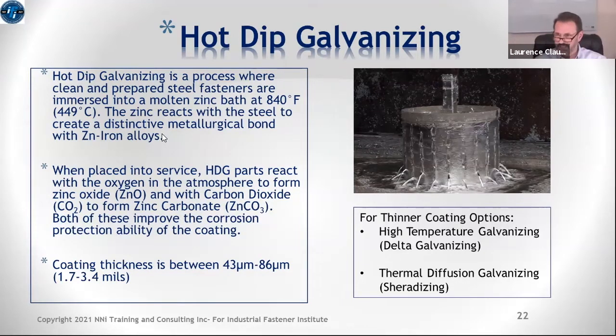If fitment is an issue, but again, hot dip galvanized type of structure is interesting to you, there are several alternatives which provide slightly less thick finishes. One is called high temperature galvanizing, goes by the name Delta galvanizing. It's not used much here in the United States. It uses a molten zinc bath that's higher temperature than the standard hot dip galvanizing. And the process that you would find more commonly in the US is thermal diffusion galvanizing, otherwise known as sherardizing.